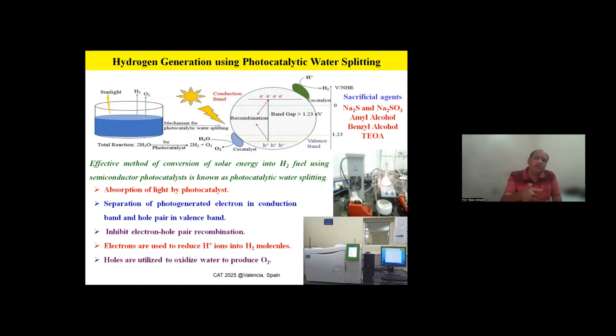Then at a particular wavelength, the irradiation occurs over the solution where the photocatalyst absorbs the light and allows the separation of the photogenerated electrons that go to the conduction band, and the hole pair remains in the valence band. And there must be inhibition of the recombination of the electron-hole pair, and the electrons are used to reduce H plus into hydrogen molecules, and holes are utilized to oxidize water to produce